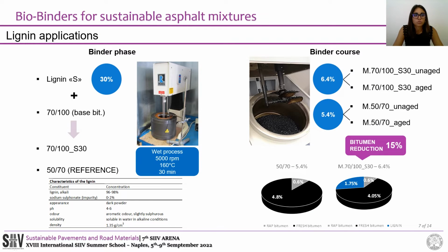In contrast to the bio-oil, which was in liquid form, a powder kraft lignin, coded as S, was selected to replace part of bitumen and obtain a biobinder. Specifically, a 70-100 penetration grade bitumen was partially replaced with 30% by weight of lignin.